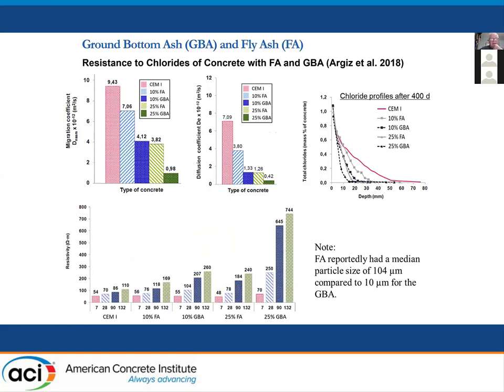And this graph shows chloride migration, chloride resistance values using the NT-492 test. And the dark green shows ground bottom ash having very good values at 20% or 25%. 10% is the dark blue there compared to CEM I. And it shows the same levels of fly ash.